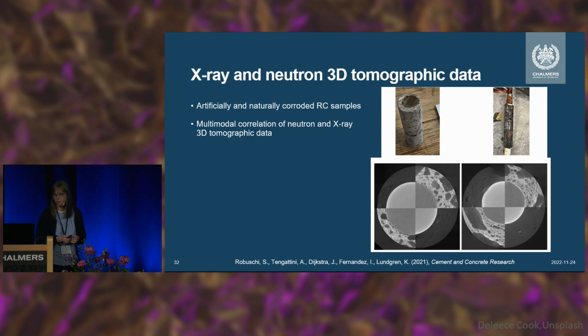And what we've been doing is looking, in this example, at both artificially corroded samples and naturally corroded samples. The artificial ones are specimens which we cast and then put current through, so that we were in control of the whole specimen and knew how much corrosion we had. While the naturally corroded ones are pieces that we took from an existing bridge, 80 years old. And you can imagine all the challenges there. Of course, you're not in control of what kind of material you have. You're not even in control of whether you have corrosion going on in the piece you have.